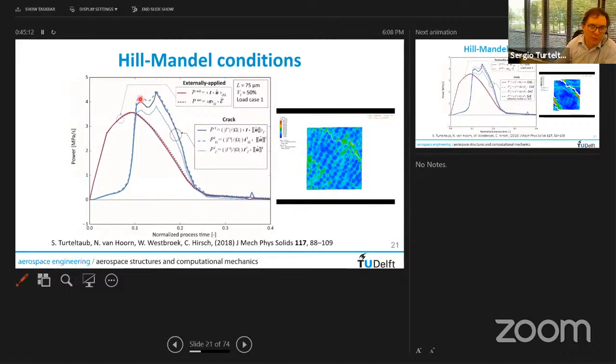The difference between the top one and the actual one is because this one is taking into account effects that happen in the surrounding material, which are not directly related to the fracture process. And, interestingly enough, the one that is just based on the average of the traction on the crack underestimates the amount of energy dissipated.